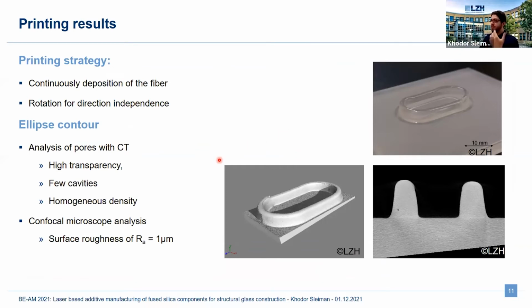And then we investigated it with CT to see how the transparency is or how many cavities are in there. So this is a picture of a CT scan, and this is like the only cavity I could find in the whole structure. We also see that the density is quite homogeneous and it is quite transparent. With the confocal microscope, we analyzed the surface roughness, which was around 1 micrometer. I think which is quite good for construction applications.